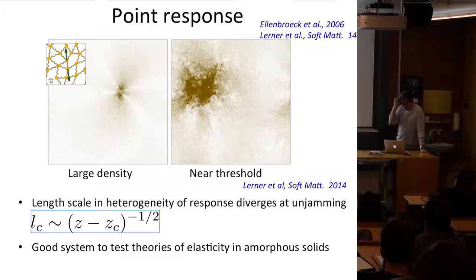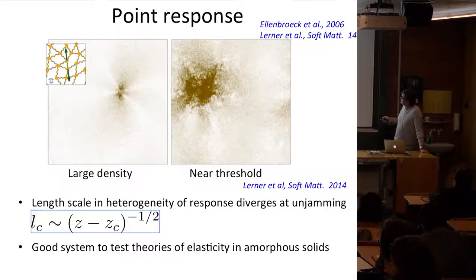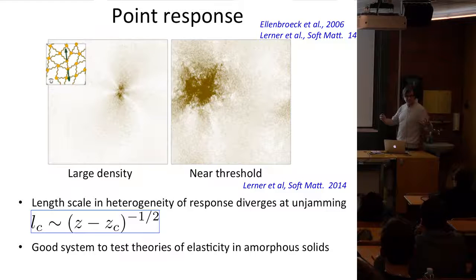All right, so now you can think about essentially everything I told you in the introduction and look at it in this system. One aspect you can look at is, again, the Green's function, the response to, for example, a dipole. If you have a system at large density, in fact this is a spring network at large coordination, but that's very similar, you see that the response to a dipole looks pretty similar to what you would get in a continuous elastic solid. But if you approach this jamming transition, then you have an entire region which is very heterogeneous. This region diverges in scale, and there was a bit of debate about what this scale is, but we redid numerics because we had a prediction, and we think it behaves like this. So it's just a very convenient system to test ideas about elasticity in amorphous solids.